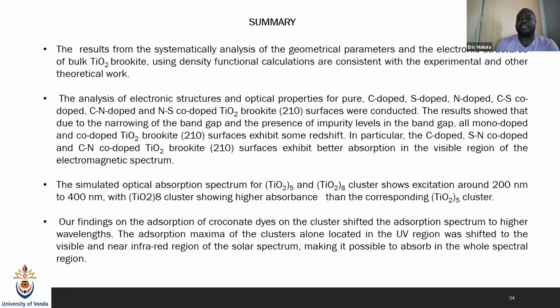The co-doping, whether with a metal or non-metal, also exhibits better results, because we can reduce the band gap. We can see the introduction of new bands, whether on the valence band or the conduction band, and whether we use the clusters or the surfaces. When we adsorb the dye on top of those, we also see that we improve the absorption towards the near infrared, or from the visible until the near infrared. And most of this improvement is because we really want to shift the high band gap absorption of the TiO2 from the ultraviolet to start from the visible to the near infrared. And that comes in handy when we adsorb the dye on top of that.